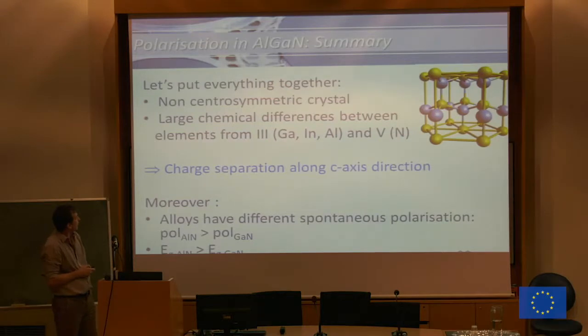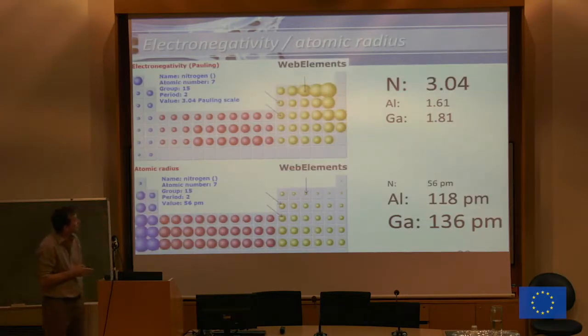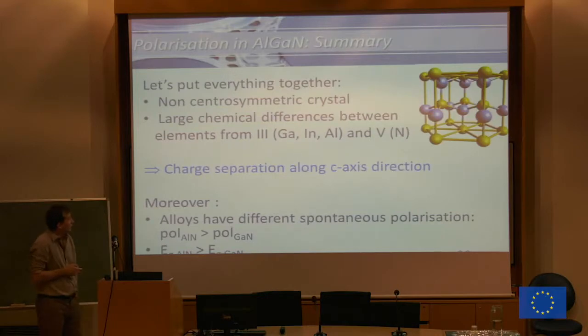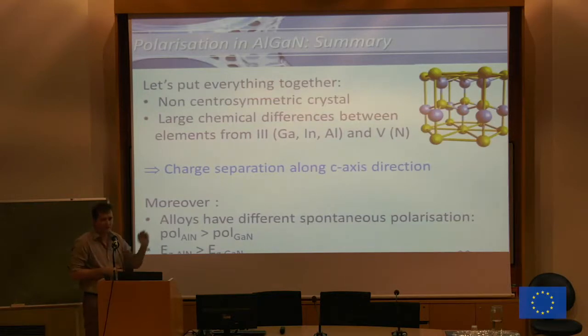Now, if you put everything together, so we have this non-centrosymmetric crystal, we have the very large differences between the elements themselves, so it's very easy to see that you will have charge separation along this C-axis. Moreover, for this spontaneous polarization, aluminium is even more different from nitrogen than gallium. So the polarization effect in aluminium nitride will be larger than it is in gallium nitride. And also, what was shown in one of the first plots is that the bandgap energy of aluminium nitride is also much larger than the one of gallium nitride.